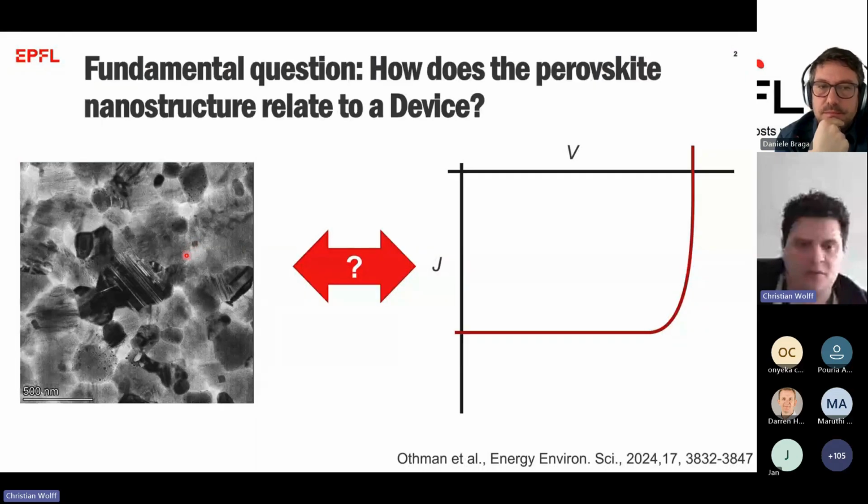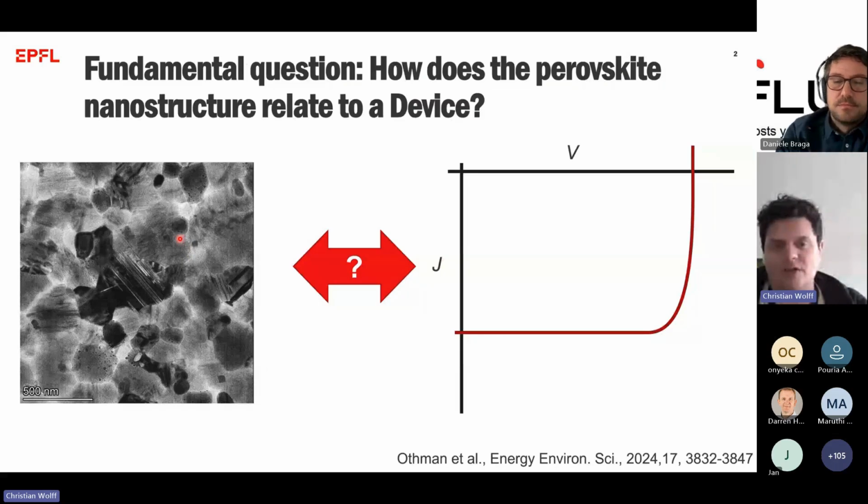This is the geometry of the electron microscope in transmission. If you were to tilt your sample a little bit, you would be able to take a look along a different, what is called zone axis, and then you would see more crystallographic contrast from other domains. So effectively, the crystal of the grains is not oriented such that you have high contrast with the direction of the electrons chosen in this geometry, but tilting the sample will give you also higher contrast in the other planes.